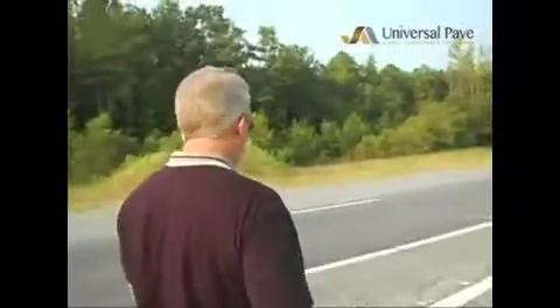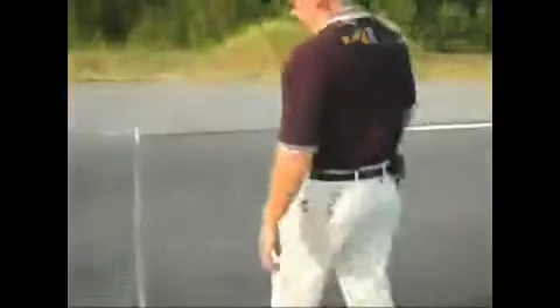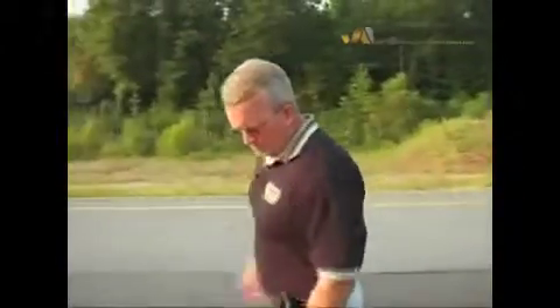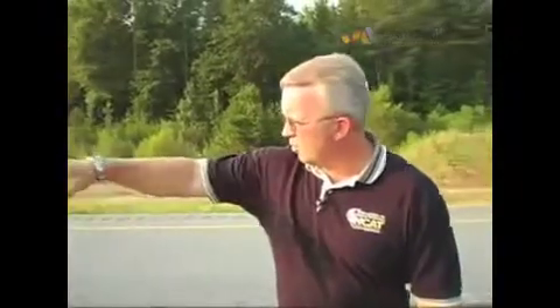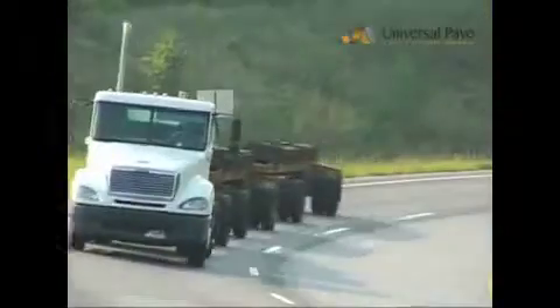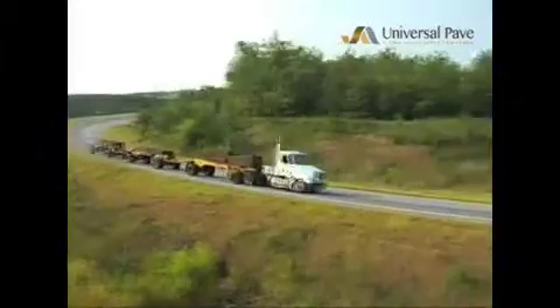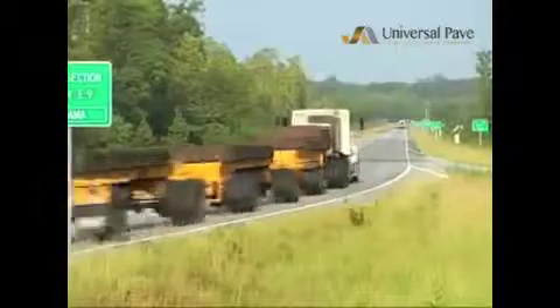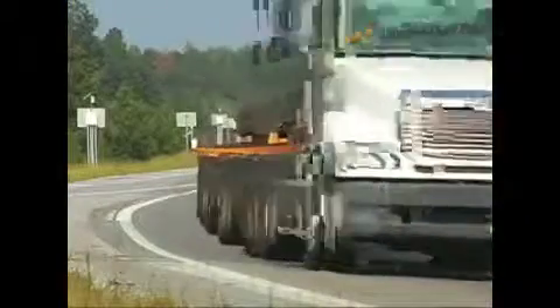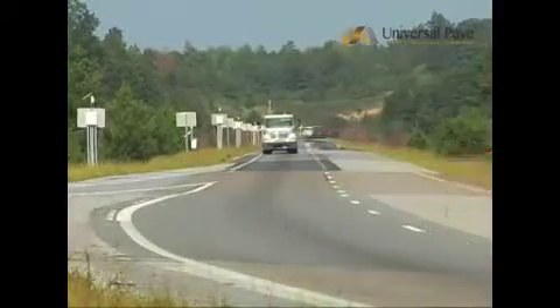Now this is the break point between E9 and E10. Buzz Powell manages the test track at NCAT, the National Center for Asphalt Technology in Auburn, Alabama. These included, and everywhere where you see a white mark going across the pavement, that's a randomly identified test location. This is an accelerated performance test, and the objective is to take 10 to 15 years worth of truck traffic and compress it into 2 years. That way we can produce results for the state-sponsored DOT within a very short period of time.